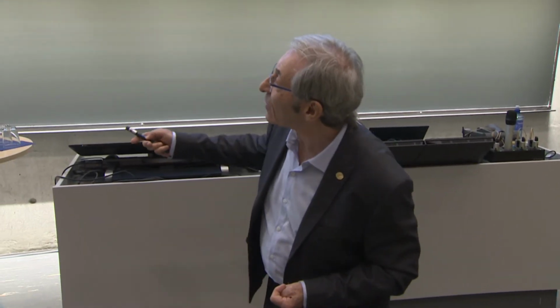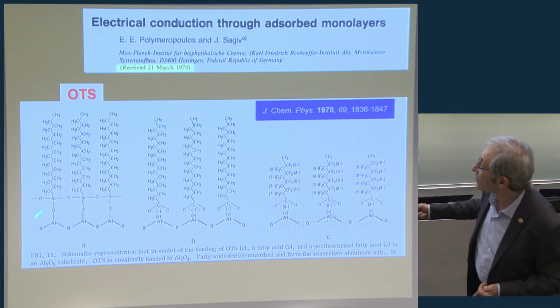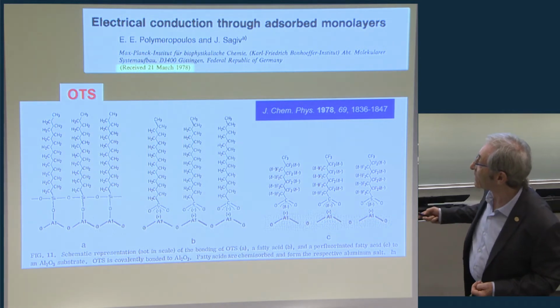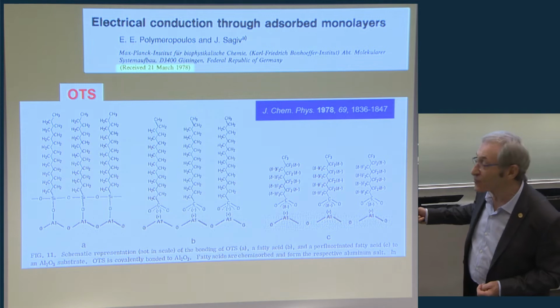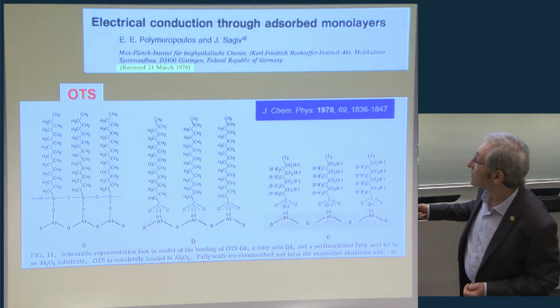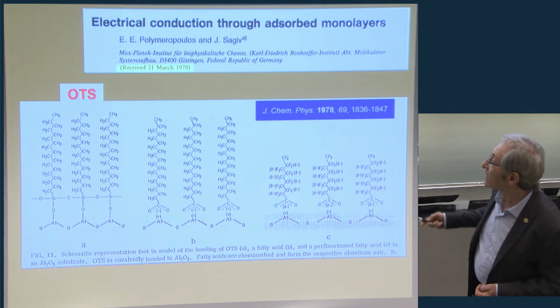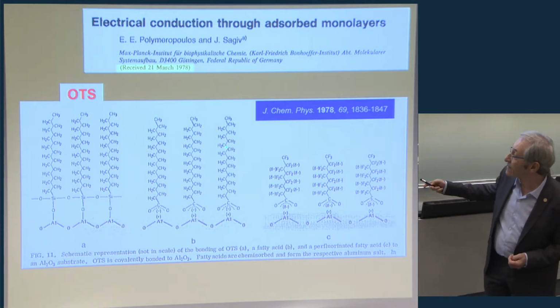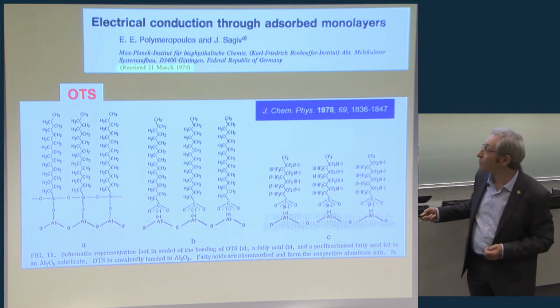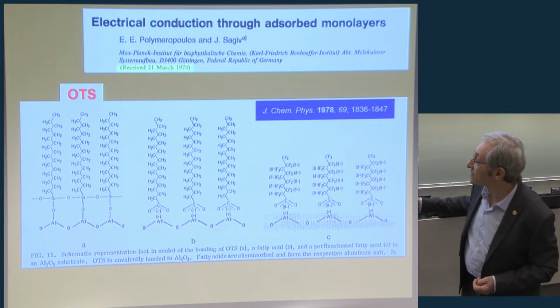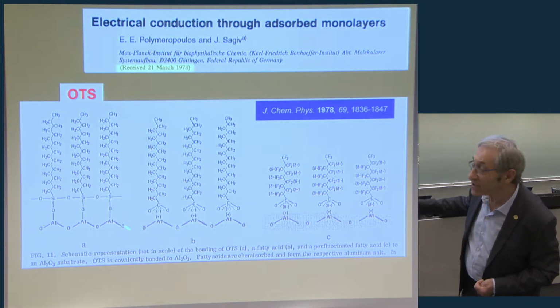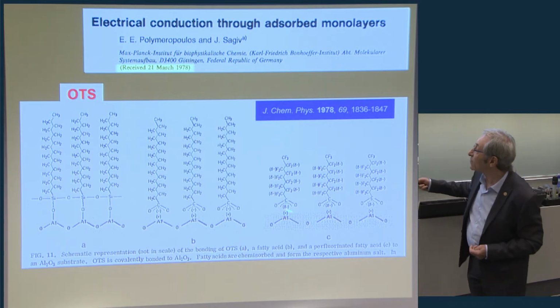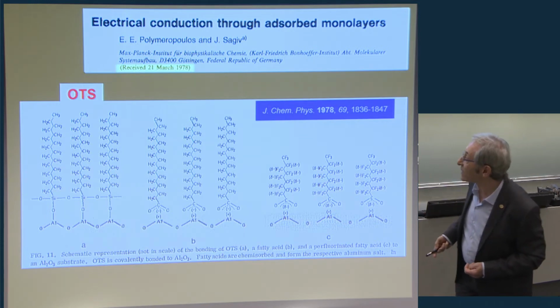Then we started with self-assembled monolayers, and this is our hero today, OTS, which has a long octadecyl hydrocarbon tail and a terminal silicon atom, and it can bind to a variety of surfaces. Here you see it on aluminum. It binds through bonds like silicon-O-aluminum. This is a very similar long-tail fatty acid that would also bind to aluminum and make a self-assembled monolayer by a different chemistry. This is making a salt, a carboxylate. And this is a perfluorinated monolayer in which all the hydrogens in the hydrocarbon are replaced by fluorine, and they also make a good monolayer.